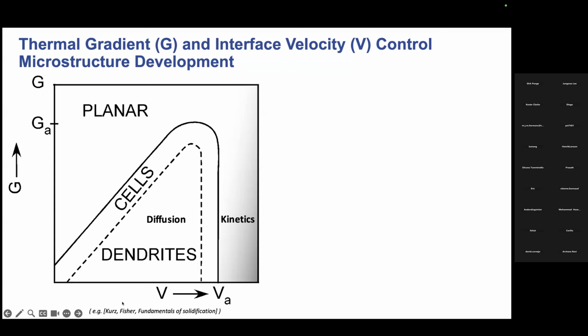And if you open a solidification textbook like Kurz and Fisher, you see a nice diagram like this that provides thermal gradient G and solid-liquid interface velocity V. And those different combinations of G and V impact the interface stability and determine the patterns that we develop during solidification. And so we can have a planar solid-liquid interface, cells, or these hierarchical dendritic tree-like structures through different G and V combinations. And really, as I mentioned earlier, our early work focused on this diffusion-controlled growth regime where things like solute and heat transport are very important.